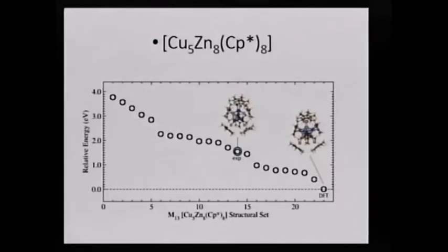The behavior is more or less the same. We have the copper atoms on the inner sphere of the cluster. However, in the lowest energy configuration, we have more segregation between copper and zinc. The copper atoms tend to stay near each other, and the ligand binding is performed by zinc atoms.